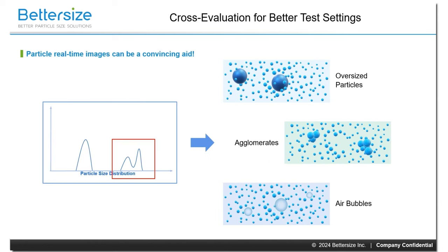Agglomerates, oversized particles, and air bubbles can cause similar results, that is the bimodal distribution. And the peak in the red box indicates some large particles. But what are they? Real-time images of Bettersizer S3+ can clearly identify the cause with particle images, and thus help us locate the problem. We can observe particles in real time with high-speed CCD cameras inside Bettersizer S3+, and the imaging methods are by their nature highly sensitive to small amounts of extra-large particles.